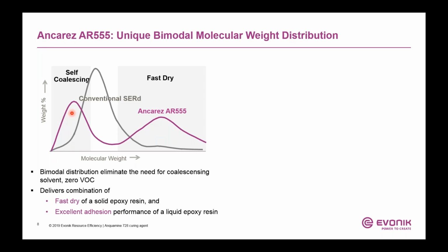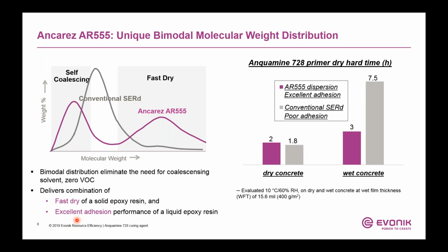So AR555 delivers not only the fast dry, but also, because of this low molecular weight portion, it gives you excellent adhesion to substrate, like concrete substrate, just like a liquid epoxy resin. So that's the uniqueness of AR555. It's excellent dry speed and good adhesion.